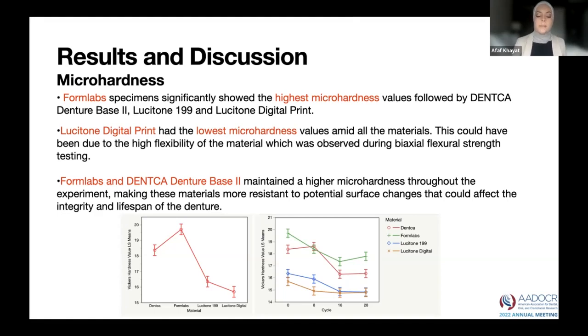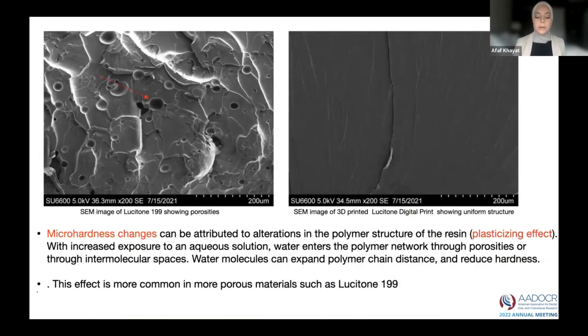Micro hardness changes can be attributed to alterations in the polymer structure of the resin, which is known as the plasticizing effect. With increased exposure to an aqueous solution, water enters the polymer network through porosities or through intermolecular spaces. Water molecules can expand polymer chain distance and reduce hardness. This effect is more common in porous materials such as Lucitone 199.